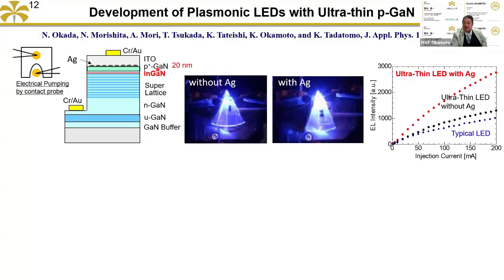But finally, we can fabricate the structure and we can obtain more than 2 times enhancement, even for the electrical pumping. For the photo pumping, we obtain more than 10 times enhancement, but the electrical pumping only gives 2 times enhancement because the optimization of the device structure is not good enough. That's why further optimization is necessary, but at least we can show this method is also useful for the electrical pumping, and the device application should be available.